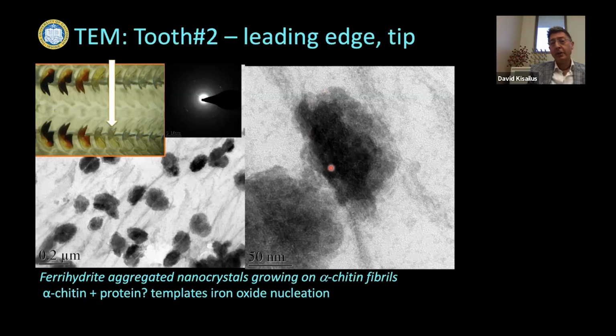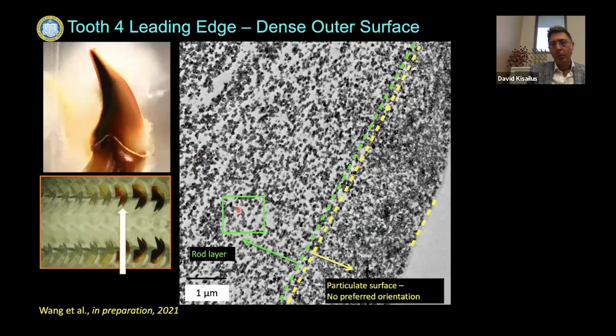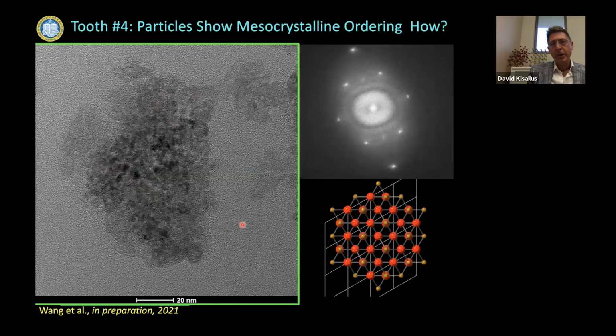The particles that are nucleating here, they look, again, like a randomly oriented or organized secondary particle with primary domains within. And our initial electron diffraction suggested that. Again, looking more carefully, this is now tooth 4, where more mineral has filled in here. Looking more carefully at one particle rather than a lot of them, we see that this secondary particle does not diffract like a randomly oriented crystal, but rather, again, like the mantis shrimp, like a mesocrystal.